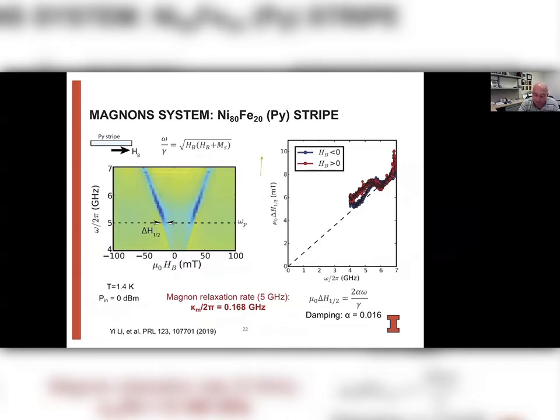But then what we can do is we can look at the line width of the excitation as a function of the excitation frequency, and we get a reasonably good linear behavior here. And by fitting this, we do get Landau-Lifshitz-Gilbert damping of around 0.016, a little higher than that. So this is not so unusual for permalloy. It's maybe a little bit higher than what you're used to at room temperature, but typically the damping actually increases towards lower temperatures. So this is pretty much as expected.